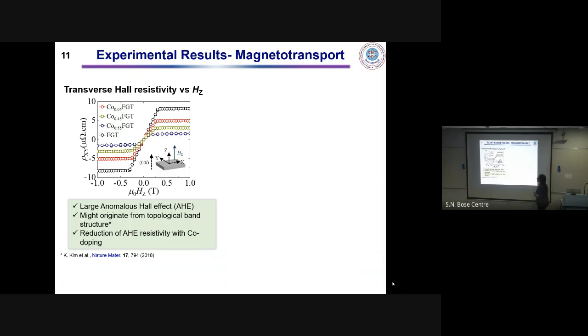And now moving on to the magnetotransport results, the most important result of our work is that here in the figure to the left, it shows you the transverse Hall resistivity when the magnetic field is applied in the z direction, that is along the c-axis of the sample, and we could observe a large anomalous Hall effect. There is one study where they have predicted that this kind of large anomalous Hall effect might arise because of a topological nodal line in this material. However, there was no further experimental evidence of this behavior. But what we could see is a large anomalous Hall effect, and the magnitude of the anomalous Hall resistivity decreases consistently with increase of cobalt doping.